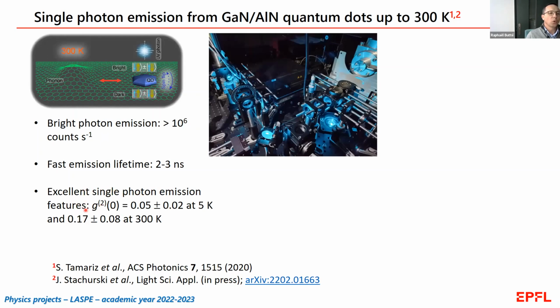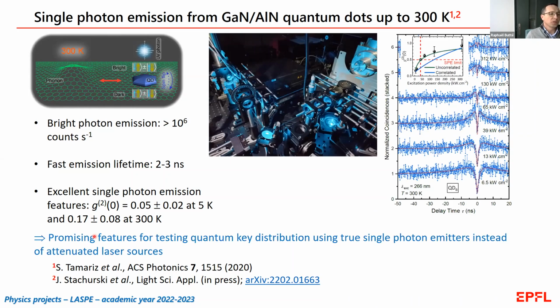So in order to quantify whether an emitter is behaving as a single photon emitter, we measure the value of the second order correlation function that should be as close to 0 as possible. At cryogenic temperature, we measured values for the g2 function of 0.05, while at room temperature, it amounted to 0.17. So this type of properties is very promising for testing quantum key distribution using true single photon emitters instead of attenuated laser sources.